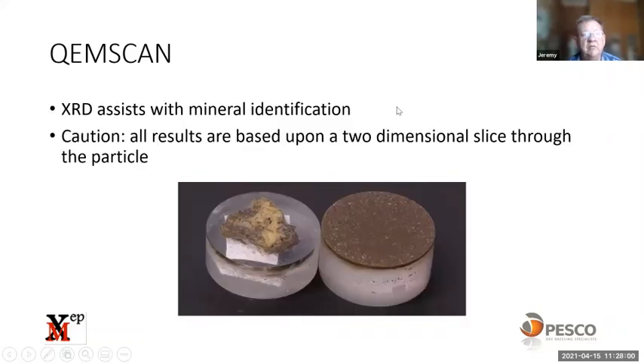So when you do QEMSCAN work, and typically you'll use this when you're looking at your finer particles, you will also do XRD to assist with the mineral identification. But you've also got to be careful, because when you prepare the sample for MLA, you mount the sample and then you polish the surface. So you're actually looking at a 2-dimensional slice through the particle and not 3-dimensional. Depending on how the particles orientate themselves when you mount them, it can affect the results.